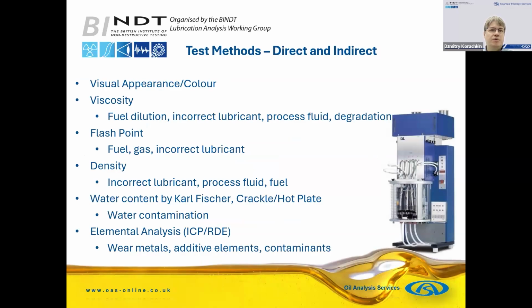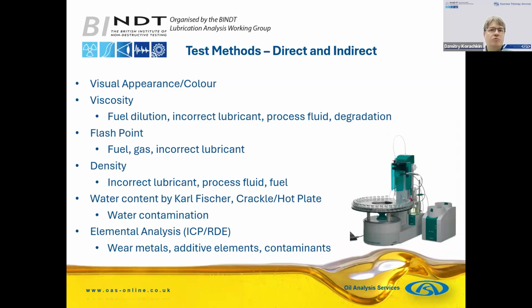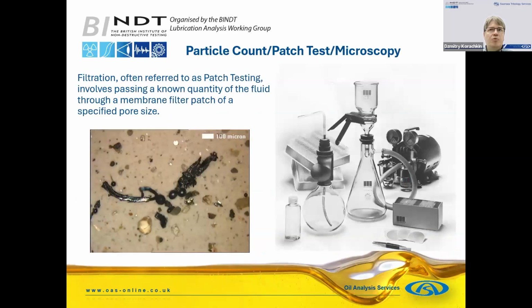Water content can be detected directly by Karl Fischer titration or crackle hot plate, infrared and so on. And then elemental analysis using either ICP or rotating disk electrode, looking for wear metals, additive elements, contaminants. Particle count may help detect ingress of